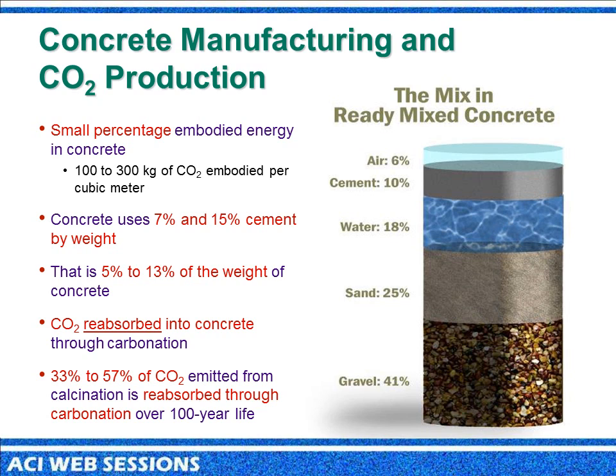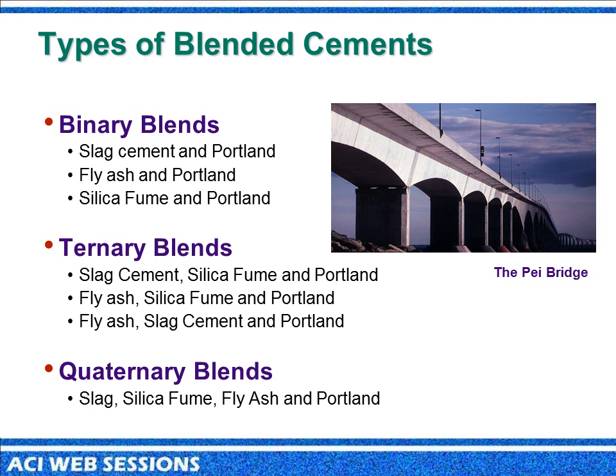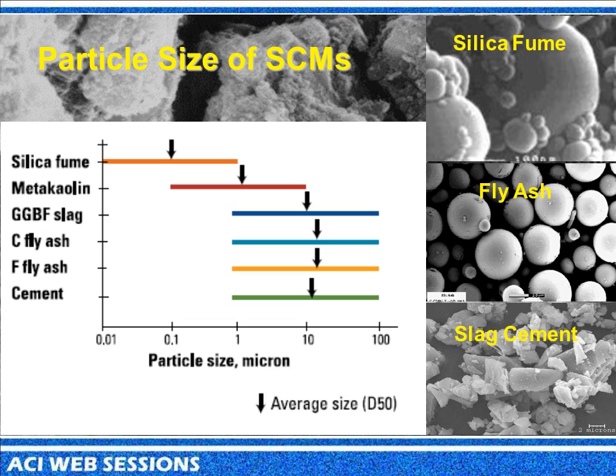We really want to look at the durable standard, because we'll see in a couple of slides that it's durability that will help us get to a more sustainable highway. Types of blended cements, we know there are many out there. The one I will focus on today is a ternary blend of slag cement, silica fume, and Portland. We're using this blend primarily because we want to take advantage of the particle size distribution that can be obtained by using these materials, with silica fume being very small in nature, and the slag cement grain being similar in size, or perhaps a little smaller than the cement grain.